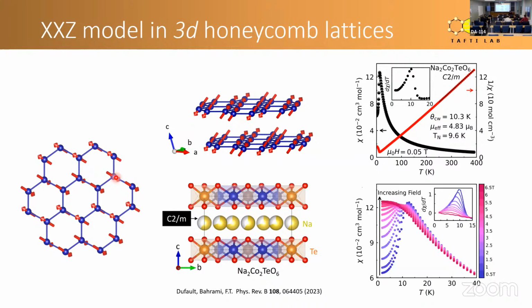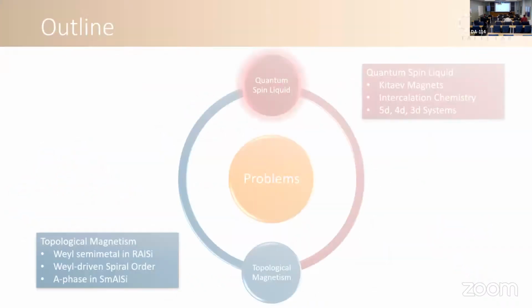And we also applied a magnetic field to the system, and we saw that the order is lifted, in fact, by increasing the magnetic field. So these are promising signs, actually, for magnetic. So basically by using an applied field, you can suppress the magnetic order in this material. Just like I showed you with pressure, you could suppress the transition temperature in silver lithium iridate.